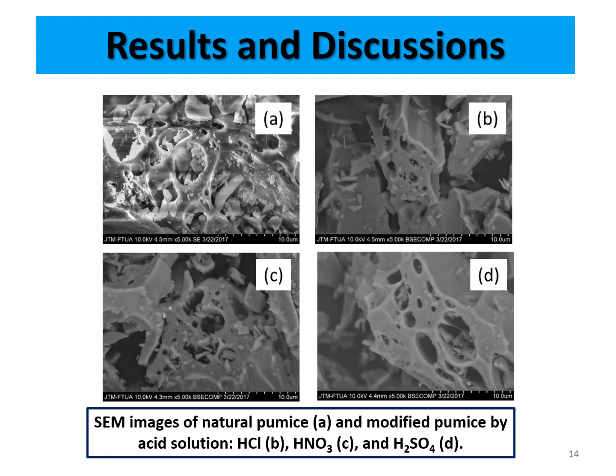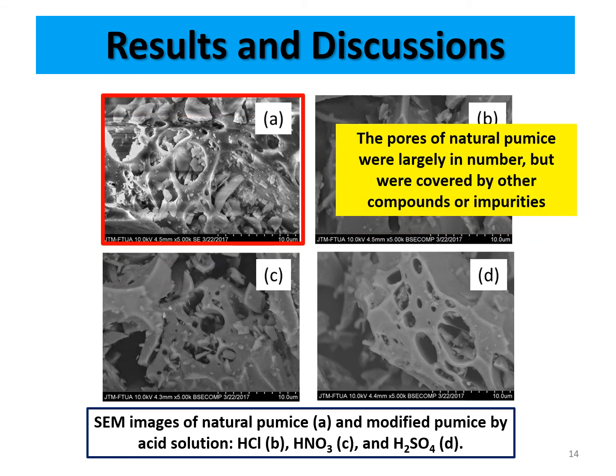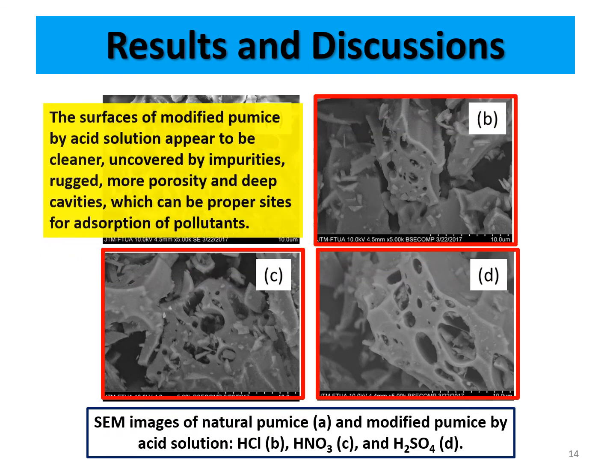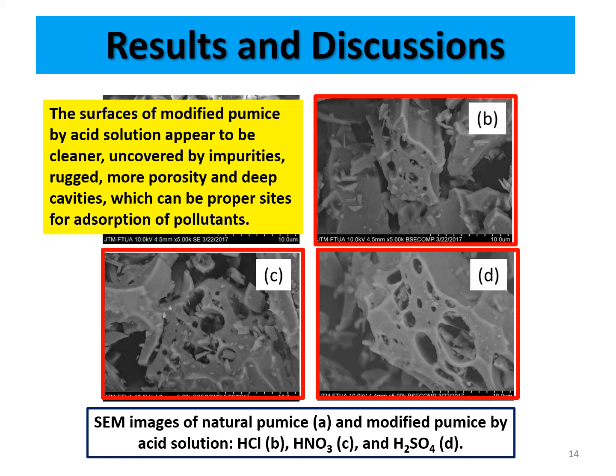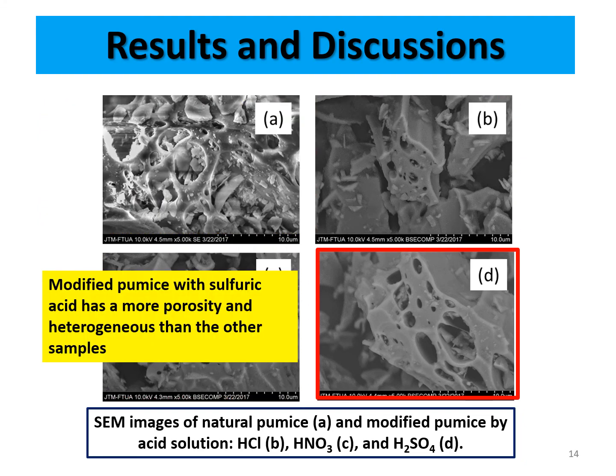These are the same images of natural pumice and modified pumice by acid solution. The pores of natural pumice were large in number, but were covered by other compounds or impurities. But the surface of modified pumice by acid solution appears to be cleaner, uncovered by impurities, rugged, with more porosity and deep cavities, which can be proper sites for adsorption of pollutant. And modified pumice with sulfuric acid has more porosity and is more heterogeneous than the other samples.